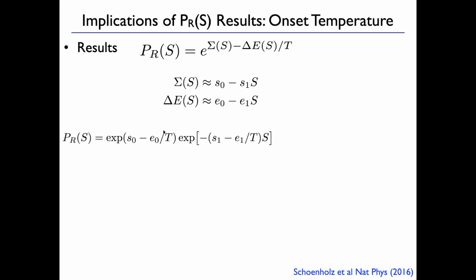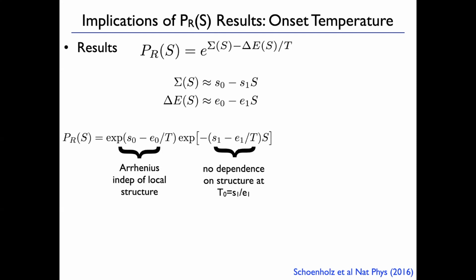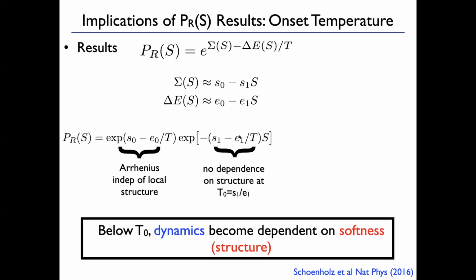It's purely Arrhenius, okay? And a second piece, which depends on structure, depends on softness here, okay? But there's one temperature here where this prefactor can be 0. But that prefactor, the probability of rearranging, doesn't depend on softness, okay? That onset temperature is S1 over E1, okay? And if I go back and look at that, so below this temperature, this is where the dynamics start to become dependent on softness, okay?